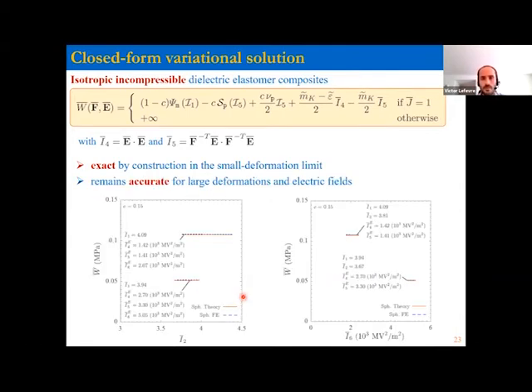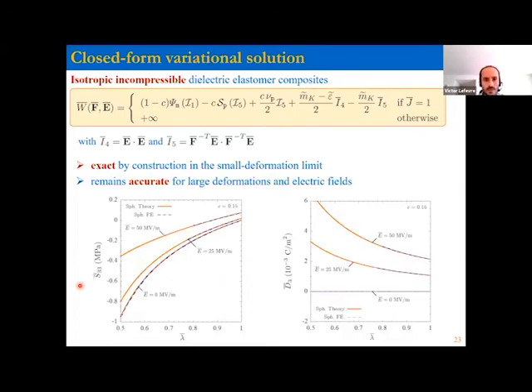For finite deformations, finite electric fields, it's not an exact solution, but it's a very accurate and very good approximation. So these are comparisons between the finite element results and the model for spherical inclusions. And you can see here, so the model is in orange, and the numerics is in dashed blue line. And you can see here that there is a good agreement between the two as far as the macroscopic energy is concerned. Of course, what we're really interested in is the derivatives of the energy. So the stress and the electric displacement. And again, these are some comparisons between the model and the numerics. And there is a very good agreement between the two.